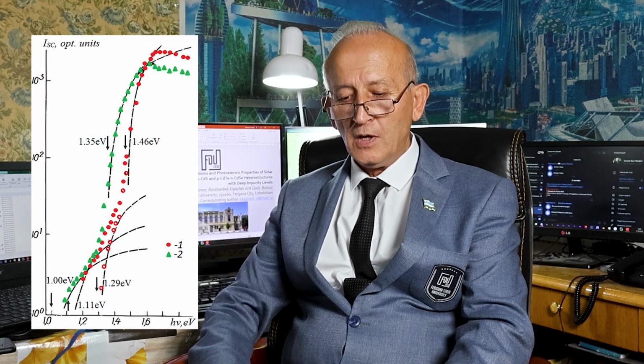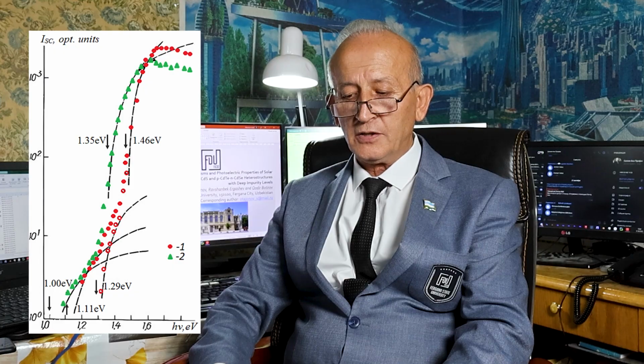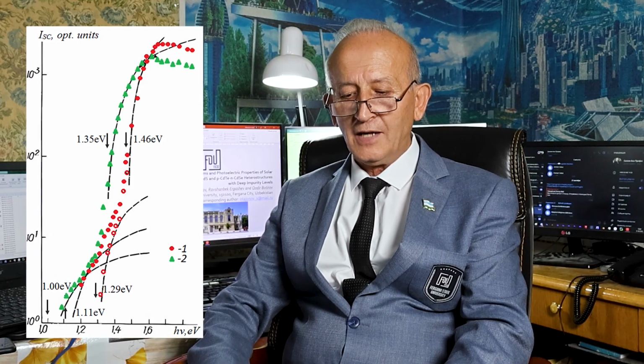Studies have shown that in all heterostructures the short-circuit photocurrent, as well as the photocurrent in diode mode, depends linearly on illumination over a wide range of its variation. As the intensity of the incident light increases, the open-circuit voltage tends to saturation. However, the absolute values of the short-circuit current and the no-load voltage depend significantly on the type of structure. They are maximal for heterostructures and amount to 20 milliamperes per square centimeter and 0.6 volts under open-circuit conditions.